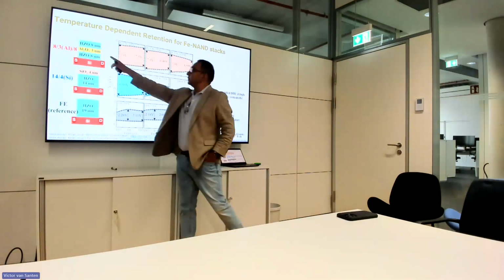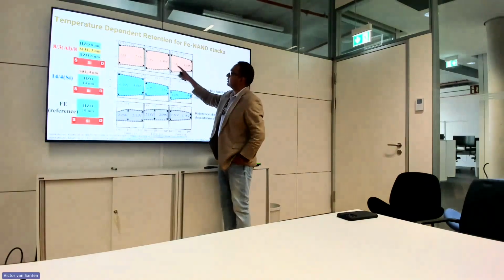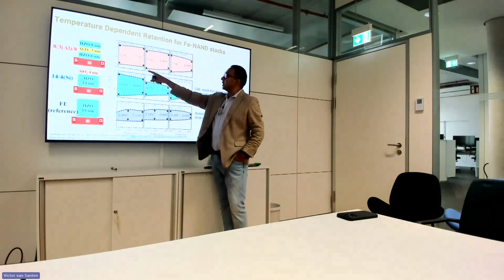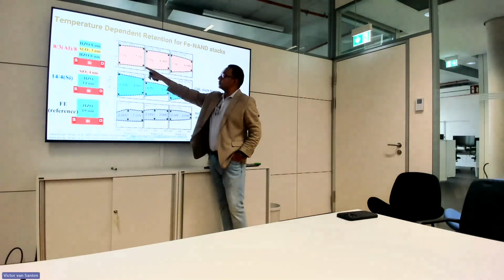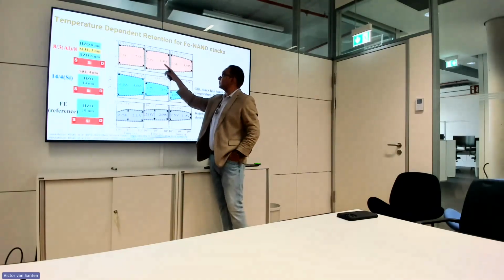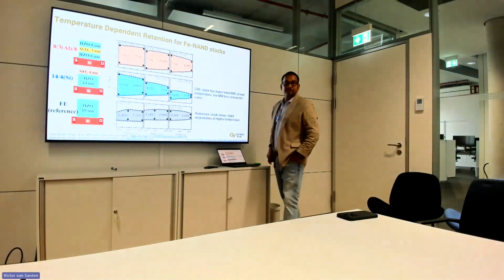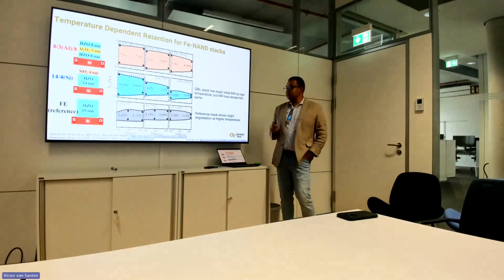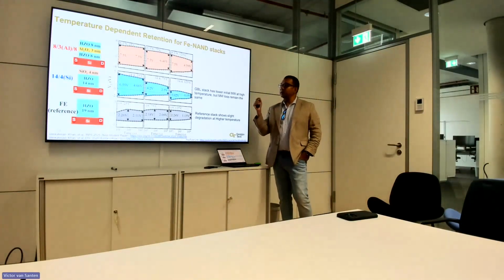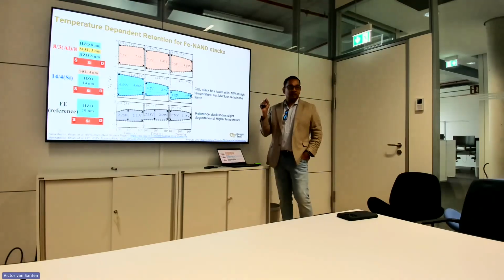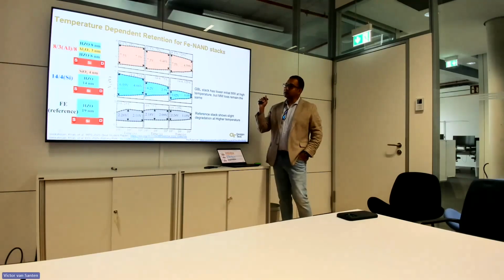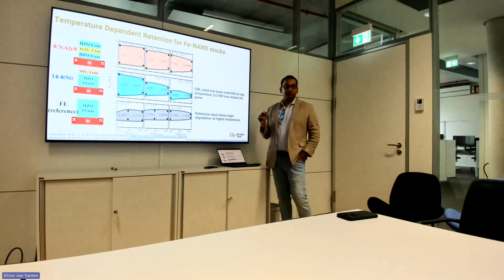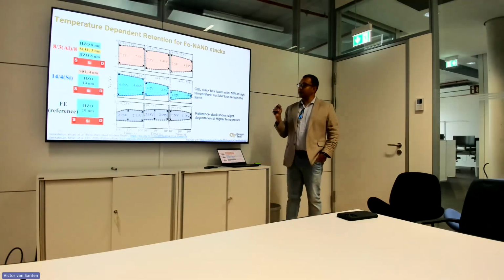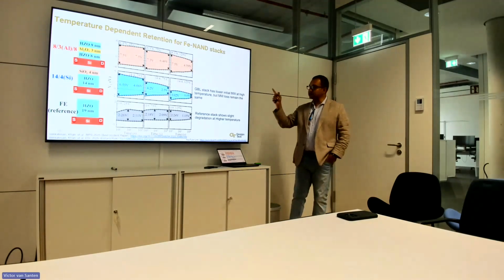But when we put the aluminum oxide in the middle, you can see that the retention stays within 10^4 seconds. There is no loss of memory window at room temperature, and even at high temperature it is much less. So the bottom line is that although the memory window can be increased by putting the dielectric layer in the middle or on the top, where you put the dielectric layer controls the retention properties. That was not obvious from the memory window characteristics, but it's obvious from the retention.